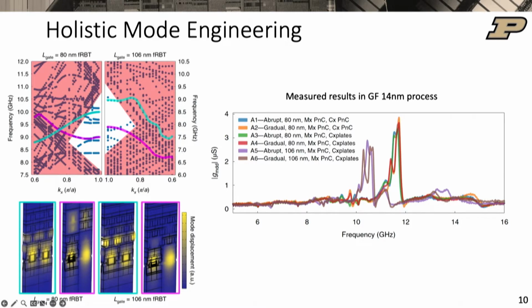So if you look here at this axis, this is the electromechanical transconductance. This is basically us applying an AC voltage to the drive capacitors and measuring an AC current out of the transistors corresponding to the vibrations, okay? So that's this transconductance, and it's in micro-Siemens. It was nano-Siemens in the case of 32 nanometers. Okay, so this is a huge improvement, but still too small to close a loop and make an oscillator at these frequencies. So some challenges there.